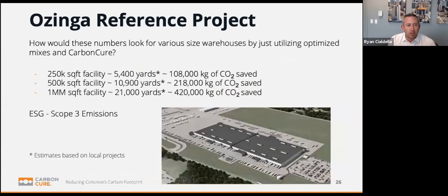And then, obviously part of this webinar is talking about parking lots and whatnot, and obviously some of these larger lots that we deal with are distribution warehouses. Just looking at some various sized projects that you would see in this market and even in other markets, based on the size of the warehouse, you've got, for example, a 500,000 square foot warehouse, which is roughly about 11,000 yards of concrete paving. And then that 20 to 25 pound per yard savings roughly translates to about 218,000 kilograms of CO2. So, that's just for the outside. If you start to incorporate that on the inside, as I mentioned, those numbers could double, if not almost triple.